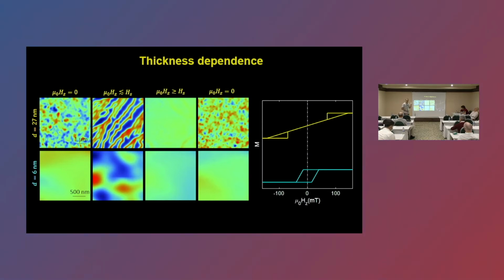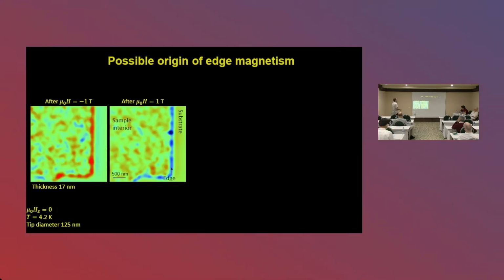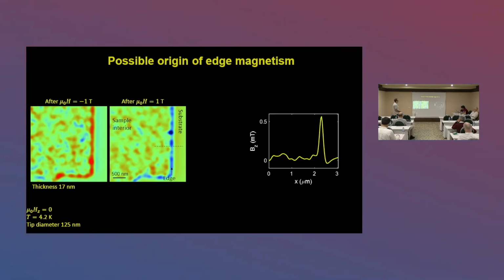But what does that have to do with the edge magnetism? If you look at one of these edges, I take a cross section, I get this peak, and I look at it in the TEM. In the TEM, you see that the edges of these exfoliated films are always sort of in a wedge shape. So they have a distribution of thicknesses, and there's always a part of the sample that will be thinner. We think that if we consider this part as being a magnet, and we know how many Bohr magnetons to expect per chromium, we can simulate this peak rather well. So you can say, okay, but how do you know that is the distribution of thickness?